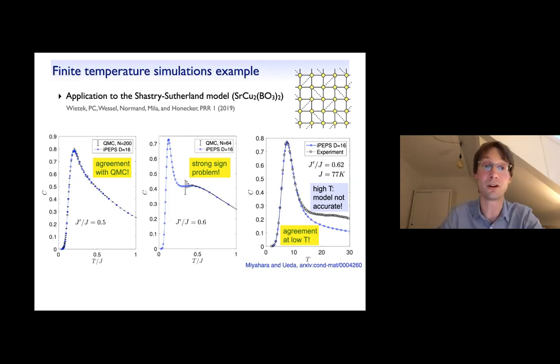What we are also doing now is to look at the problem of strontium copper borate under pressure, where essentially you go to larger coupling ratios, and at some point there's a phase transition into a plaquette state, which is no longer a trivial ground state. And of course, that's much more challenging than what we do here. But it's a very good question.